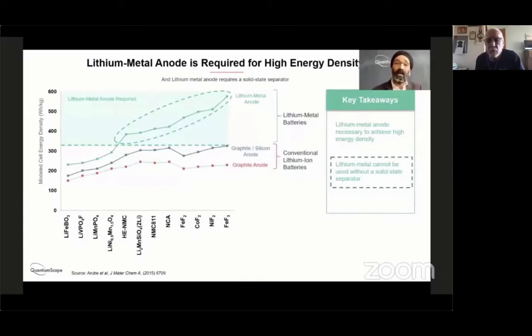That's obviously a catastrophic failure, and the only way to address that is to switch to a solid-state separator, which can prevent lithium metal dendrites from forming. So the industry has known all this since the mid-70s, but that's where the industry's been stuck, because it's turned out to be very, very difficult to make a solid-state separator that meets the requirements of conductivity while being able to prevent lithium metal dendrites from forming.